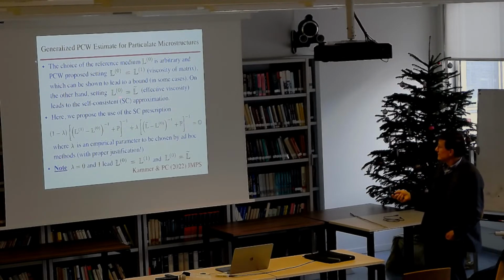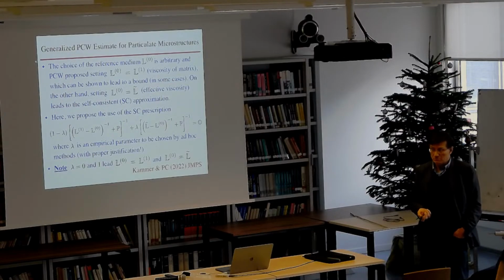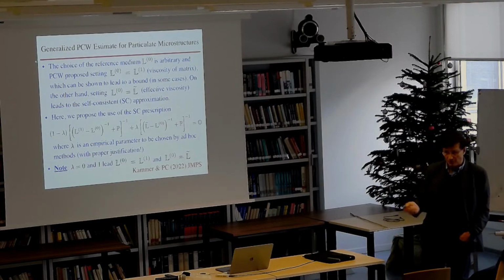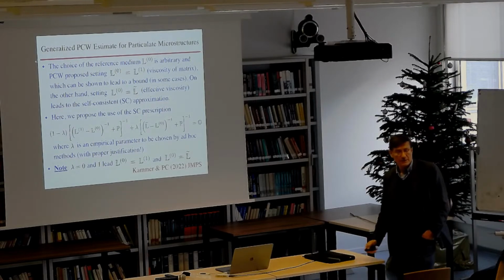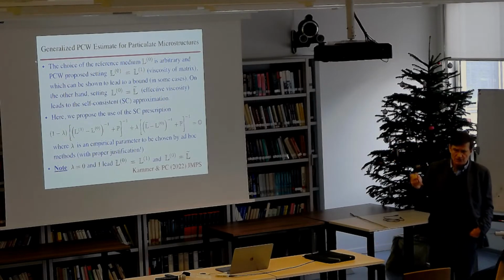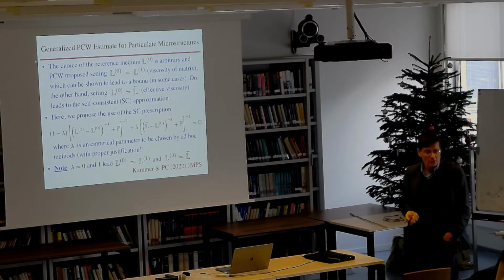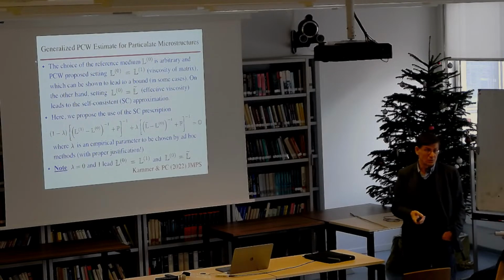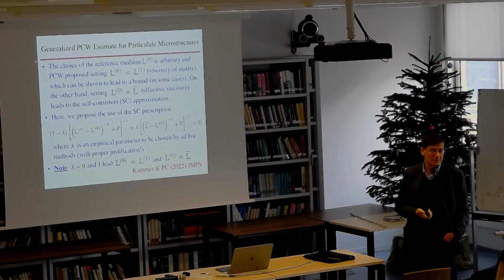This effective medium approximation has some interesting properties. It also linearizes for dilute concentrations, which is also a good estimate. But once you get to large volume fractions, particularly if particles are rigid, you get a percolation phenomenon where the properties blow up at a finite concentration of particles, and that, for spherical particles, that value is too low.